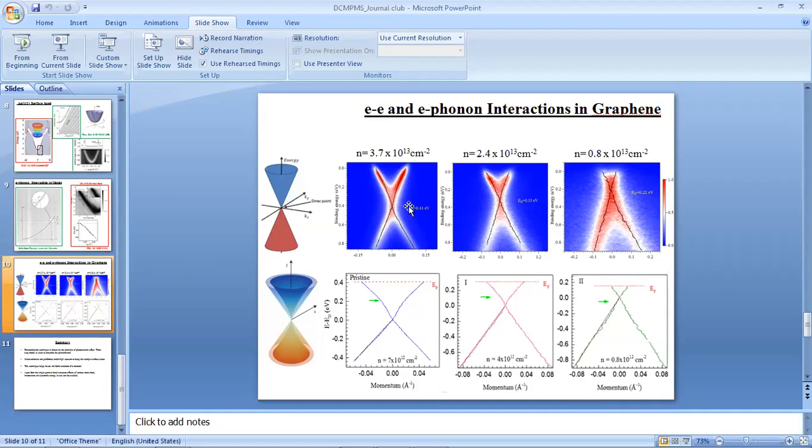Okay. So here, from this figure, you cannot find out where the crossing is. It can be anywhere inside this region. So for that we have to perform the experiment in some other way. We do the experiments with some other photon energy with varying polarization, where only this band or only this band is seen.